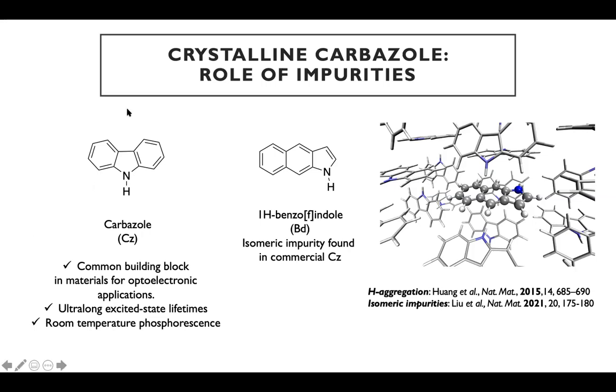Another good feature of carbazole is that it shows room temperature phosphorescence. And for many applications, it's good to have phosphorescence at room temperature. So it's interesting to look at the reasons for that behavior. Something interesting that experimentalists have found is that there were different kinds of reports about these molecules. I mean, different groups reported different quantum yields for these processes, and that seemed to be related to impurities or defects in these systems. A recent work, from the beginning of last year, that appeared in Nature Materials, analyzed the effect of impurities or organic dopants in these processes. And they did a lot of experiments trying to find out, and we then went back to the processes and tried to understand what was going on.